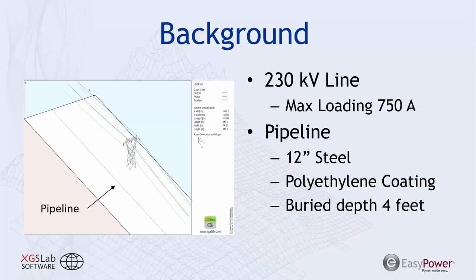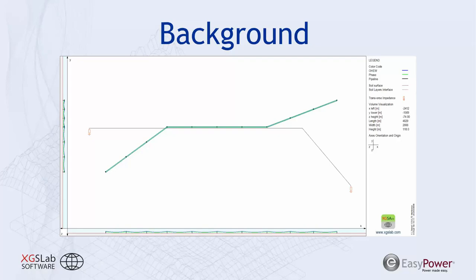And the exposure length of this transmission line on the pipeline is approximately 1 mile, where we're directly parallel. And we will have some effects as the transmission line crosses over the pipeline and then departs away from the pipeline. And we'll see that in our voltage plot on the pipeline, as well as our amps per meter squared plot